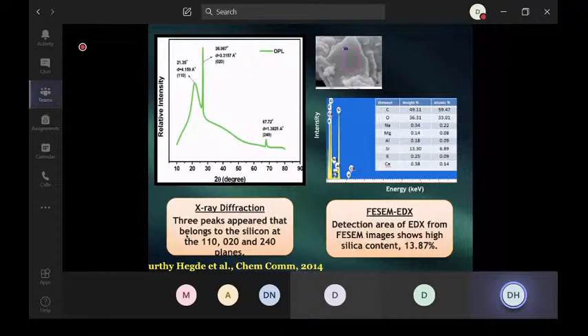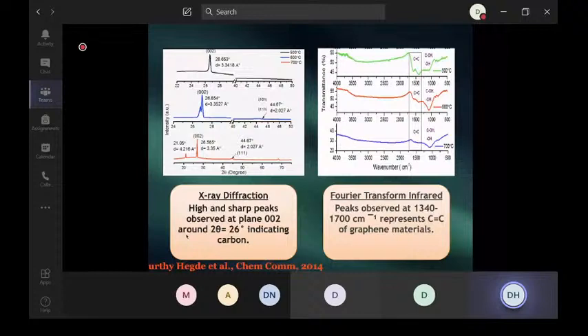And then we made the nanoparticle. Once we make a nanoparticle, we have to characterize it with various techniques to prove that the synthesized particle is a nanoparticle. First, we did XRD, and you can see very sharp peaks, which again surprised us, because whenever you synthesize nanoparticles from bio-waste, you always end up with amorphous peaks. You never get crystalline peaks. But in this particular OPL, you ended up with very beautiful crystalline peaks.